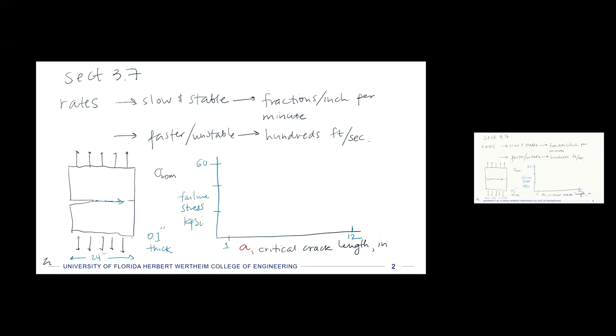When you have a critical crack length that is very long, like 12 inches, which would be half the way across this plate, then the failure stress is at its lowest. So you would get a point about here, and in this case this is for a particular aluminum alloy. At the opposite end, if the critical crack length is 1 inch, then we have to pull with a lot higher stress to get that thing to break, so we're up here at almost 60 kpsi. Then the data points will go sort of like this. We don't really approach something asymptotically like we do with the SN curves, but we get this kind of inverse type relationship. I'm going to draw the line as they've drawn it in the book, even though it doesn't fit through all the data points.